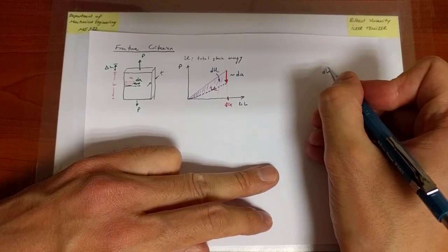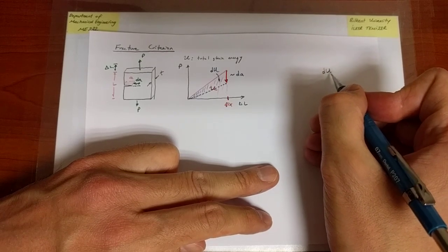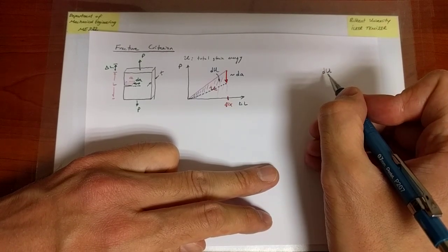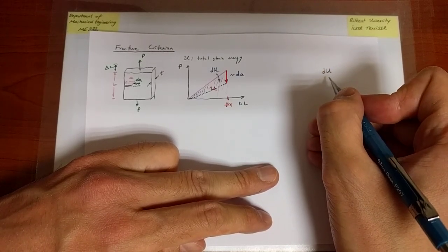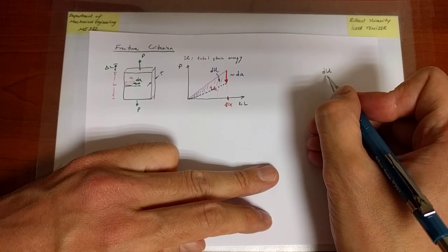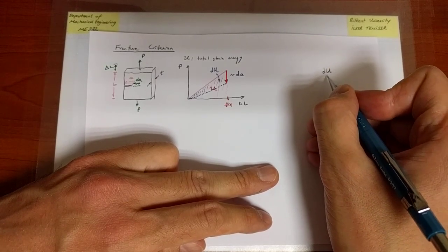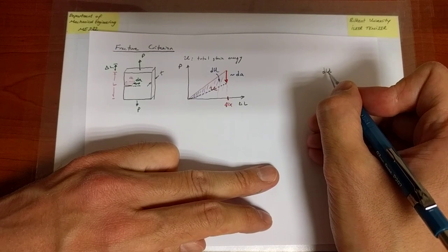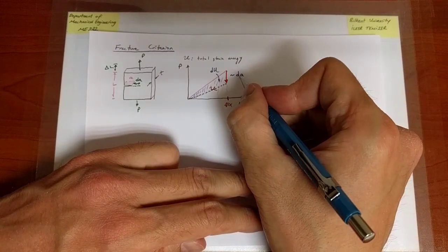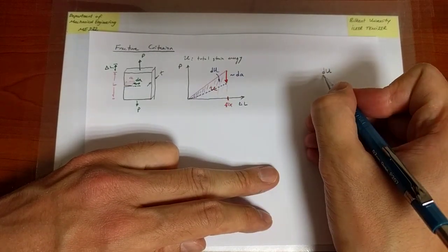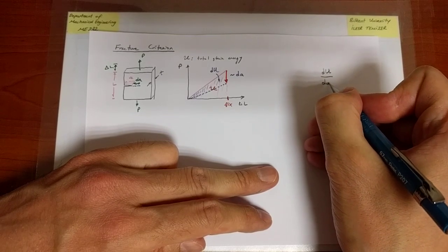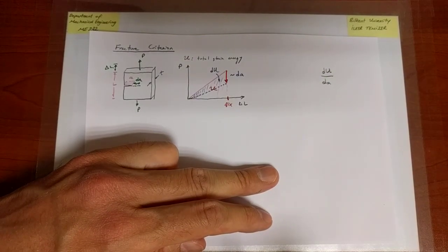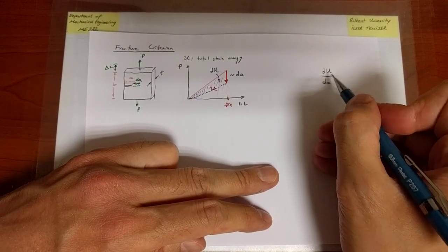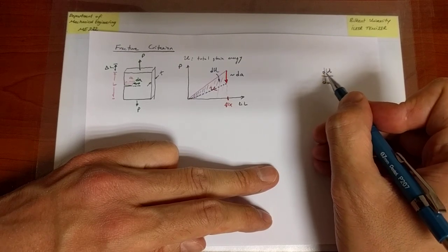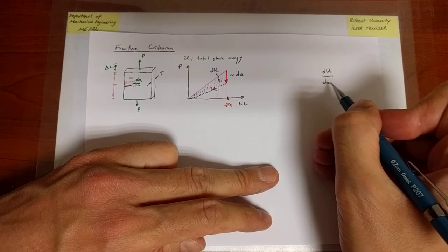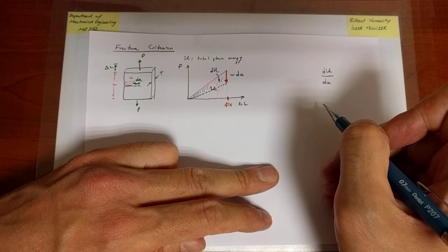So I can easily do that by looking at the change in the energy. Okay, so that's the amount of energy, strain energy, elastic strain energy that has been removed from the system. And the amount of energy that has been removed has to do with the amount by which the crack propagates. And therefore, for a unit propagation of the crack size, this is the amount that has been released from the system, the ratio of dU to dA, the amount by which it propagates.